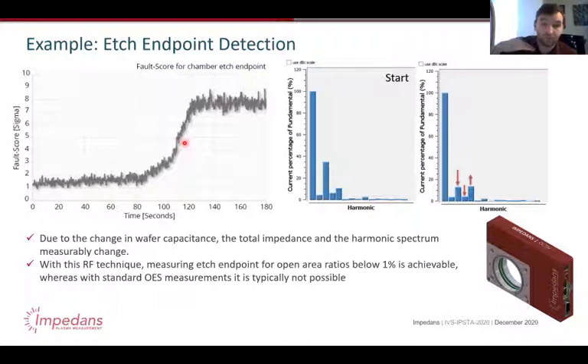If most of the wafer is covered in hard mask and say only 1% or less of the wafer is exposed to the etching, that's very hard to measure optically. Normally you measure that optically, but the signal to noise ratio makes it very hard to get reliable data. But there are a lot of publications that show RF and impedance monitoring is the way to go, because the capacitance of the wafer dominates the capacitance of the chamber. It's actually the dominant component.